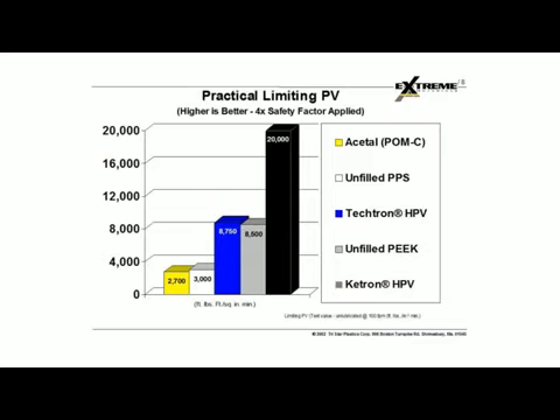So obviously the lower the number, the lower potential it is in terms of its bearing capabilities. But you can see here that Techtron HPV is rated at 8750. The Ketron HPV, just because of its inherent capabilities in terms of higher PVs, is up to 20,000, and these numbers are with a four times safety factor. So if you consider that, the Techtron HPV material is a very, very good bearing material for a lot of the mid-range load and speed applications.